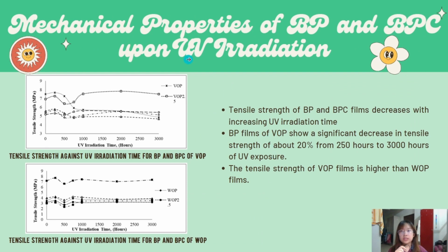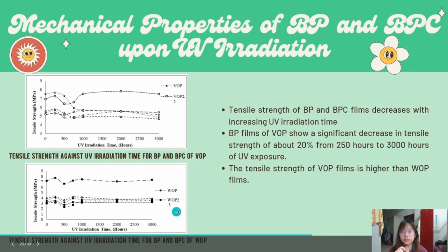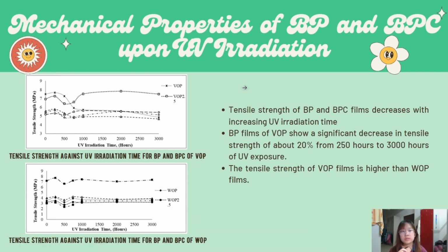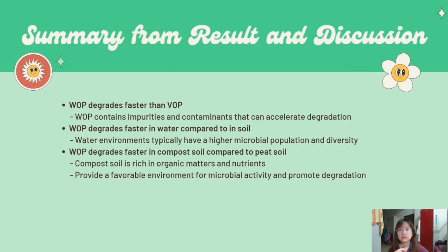The last one is the mechanical properties of BP and BPC upon UV irradiation. These two graphs indicate the tensile strength against UV irradiation time for BP and BPC of VOP and WOP. The tensile strength of the BP and BPC films decreases when the irradiation time increases. Therefore, in short, the tensile strength of the VOP film is higher than the WOP film. So, based on the results and discussion, we know that the WOP waste oil polymer degrades faster than the virgin oil polymer.